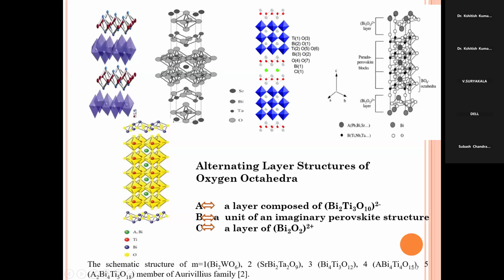But now the question is, from the 1 layer, 2 layer, 3 layer, 4 layer, and so on, we cannot extend the layers beyond the 5th, because the 6th layer does not exist. But among the 1, 2, 3, and 4 layer, which one do we have to choose? We went to the literature, where different researchers have worked on materials with 1 layer, 2 layer, 3 layer, and among those we have found out which material is the best according to the property.